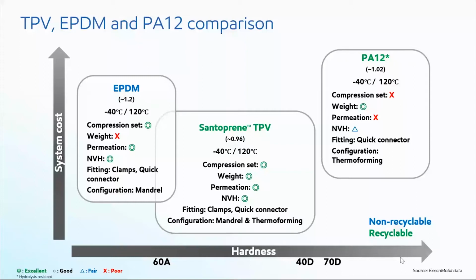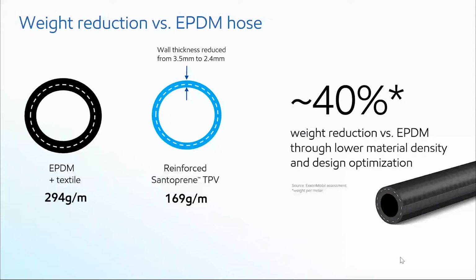So moving on, let me give an example or a case study wherein we converted an EPDM coolant hose to a Santoprene hose by doing some design optimization. You can see here the EPDM hose with a reinforcement was about 294 grams per meter. When we did the design optimization, we could reduce the wall thickness because of the properties of the Santoprene. We reduced the wall thickness from 3.5 millimeter to 2.4 millimeter. So finally, the weight came down to 169 grams per meter, meeting all the requirements. So we got approximately 40% weight reduction by converting from EPDM to Santoprene TPV.